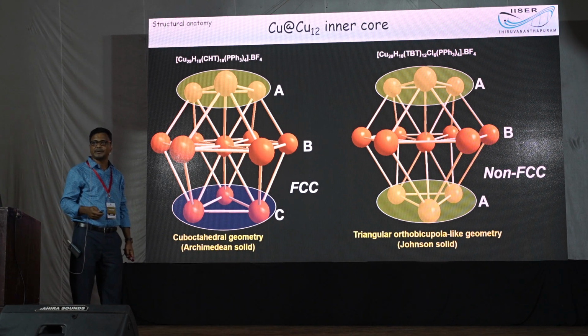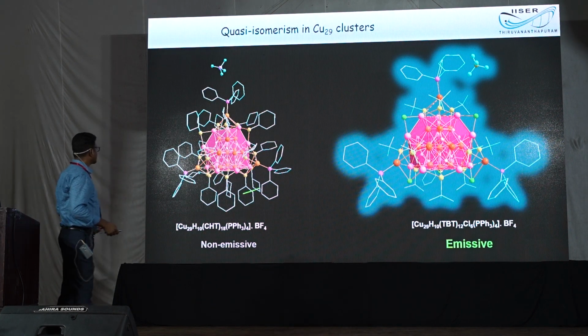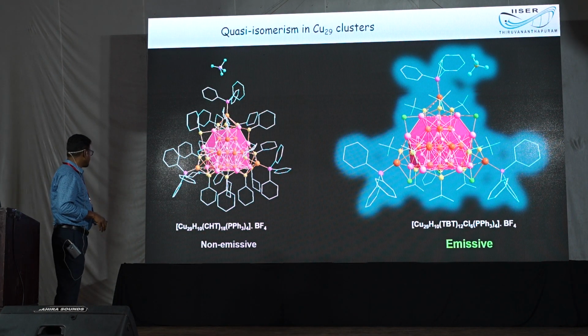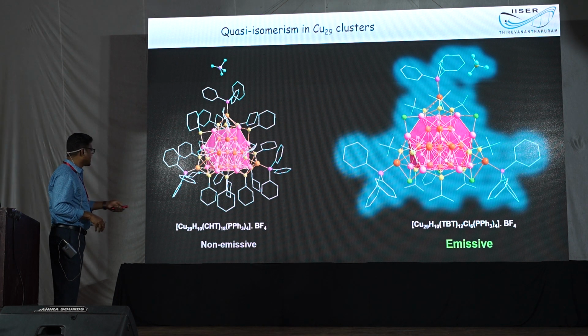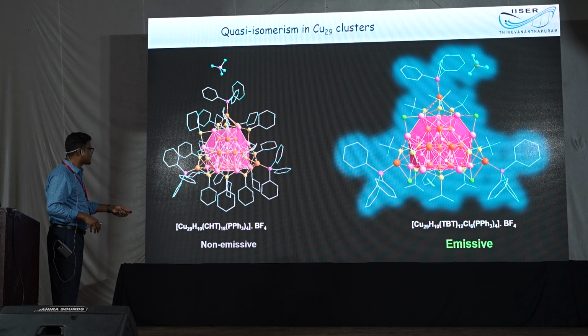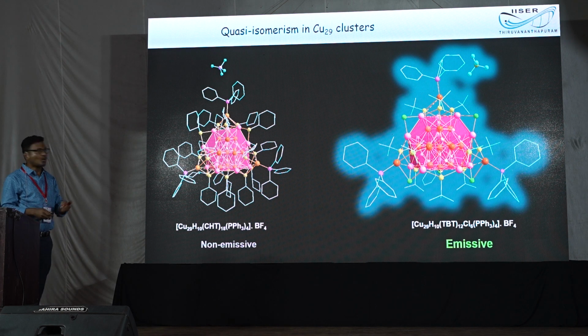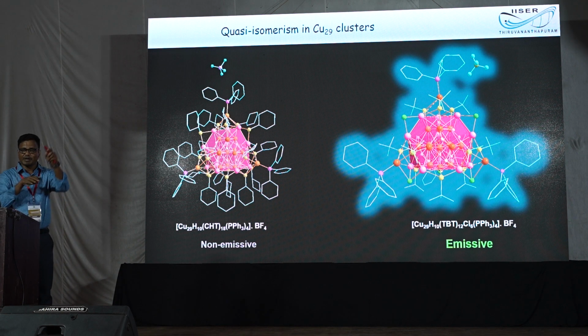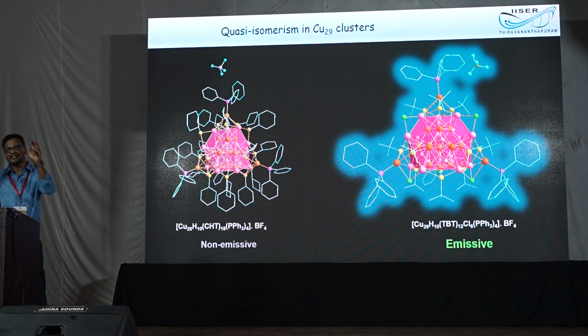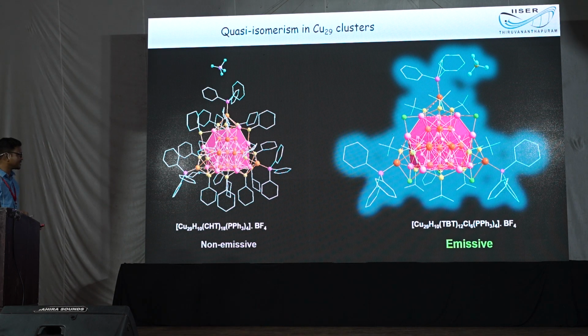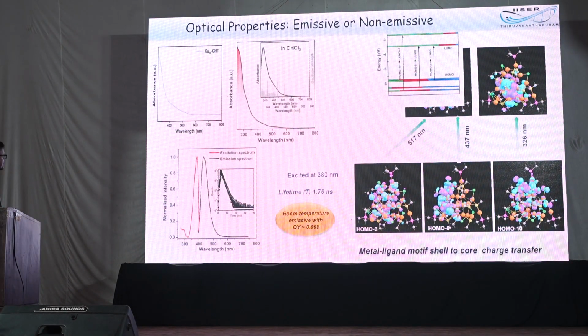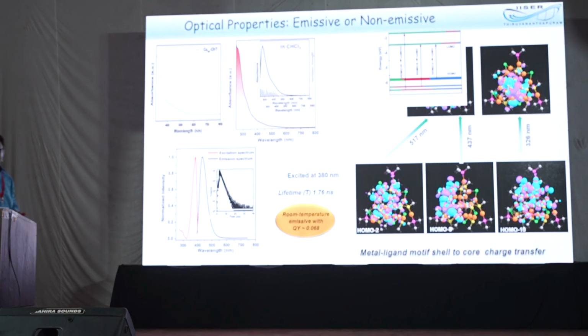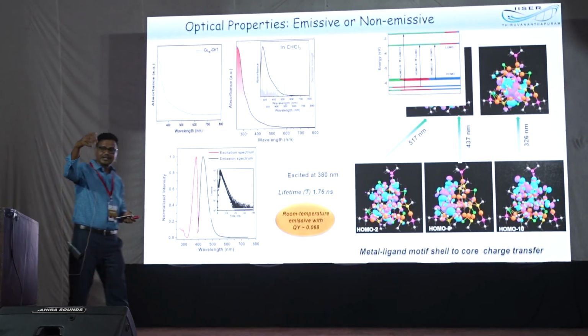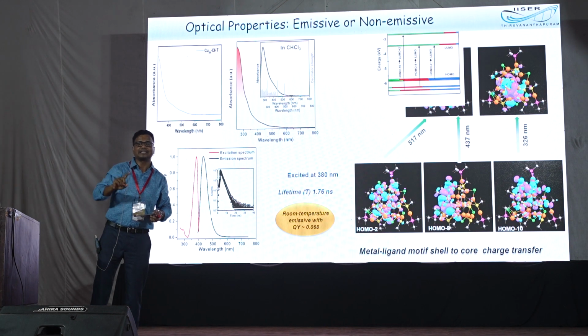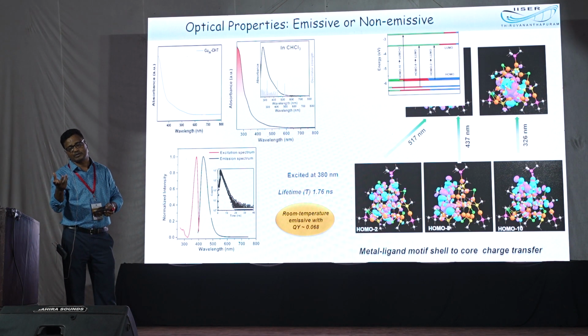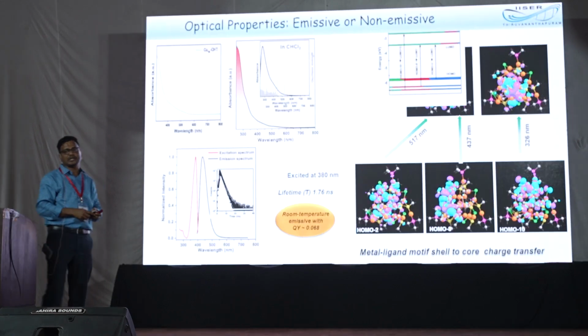Then we have done the room temperature emission. We can see that the cluster with the FCC kernel is non-emissive, and this one, the tertiary butyl thiol, is the emissive one. All other things are the same, only the arrangement of the kernel, FCC versus non-FCC, is dictating their optical properties. So why is this happening? Because theoretical calculation shows that the atomic arrangement and different connectivity contribute to the frontier molecular orbitals, which are responsible for the electronic transition.